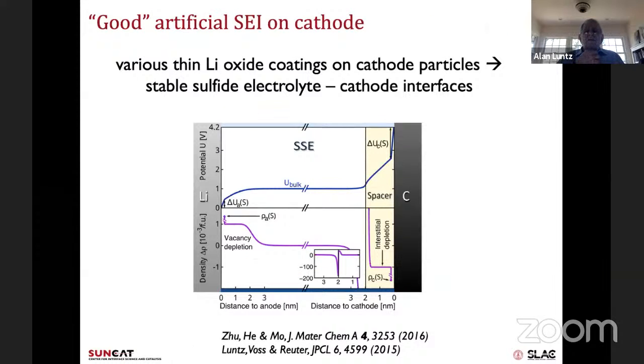So what has been quite successful with the sulfide electrolytes right now, and actually with the oxides too, I think, is you put thin lithium oxide coatings on the cathode particles, nanometer-thick things. These are materials like lithium niobate, lithium tantalate or lithium zirconium oxide. They're thermodynamically stable against both the cathode and the electrolyte. And so what happens is you drop most of the chemical potential across these nanometers of stable materials, and then you're at a low chemical potential in the solid state electrolyte so that it's thermodynamically stable.